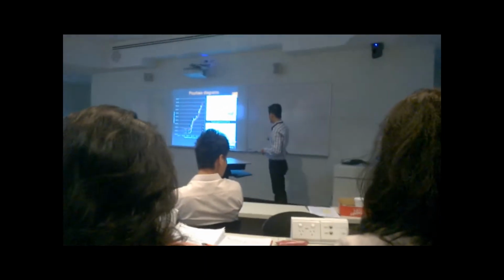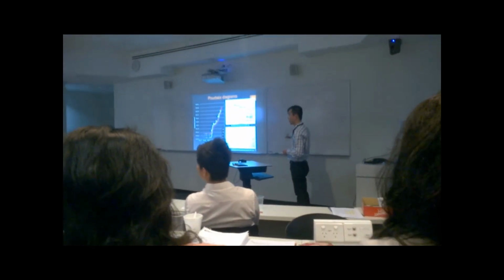The top region is the corrosive region, where it reaches there and it might corrode. Looking at the curve here, the first point of the carbide is sitting here. So the carbide is sitting in the cannot-corrode region, so it's still stable. When you bring it to the second potential, the carbide gets dissolved in the solution.